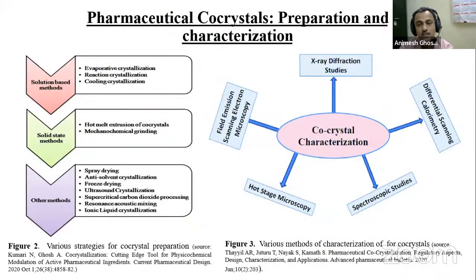So these are the pharmaceutical co-crystal preparation and characterization. There are mostly three methods. One is solution-based methods. The most important is evaporative crystallization, also known as solution crystallization. Next are reaction crystallization and cooling crystallization. These are all solution-based. Then solid-state methods, like hot melt extrusion of co-crystal, because in hot melt extrusion, if we can melt both drug and coformer and allow them to crystallize, there might be an option to get the co-crystal. And mechanochemical grinding, that means if we grind in a ball mill or a high-speed mill, in that case we can get this.